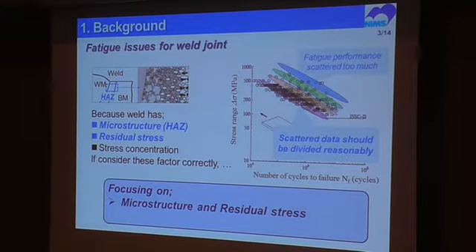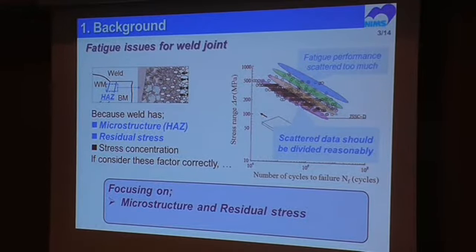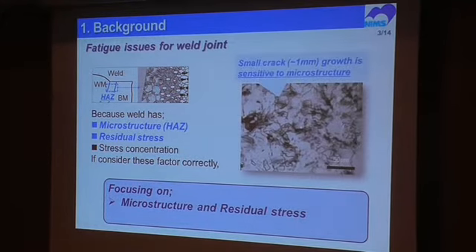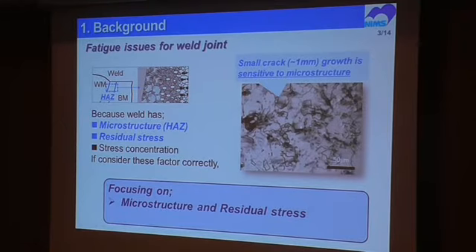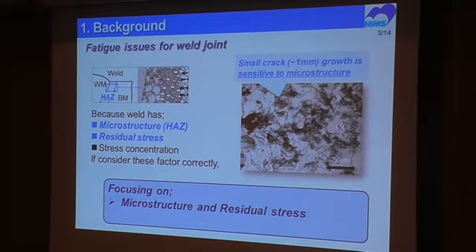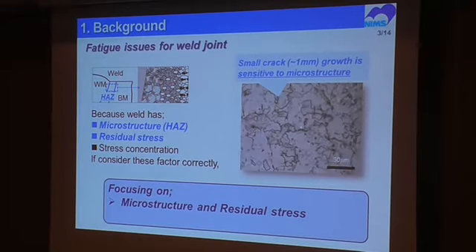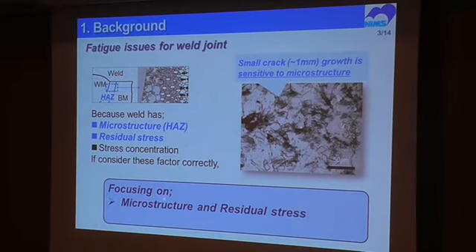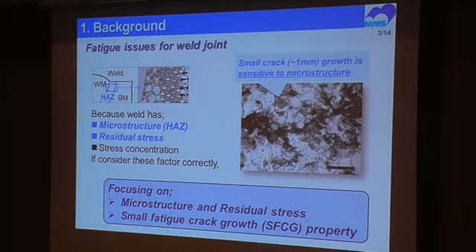So, to develop the evaluation method for these complex effective factors, this study is focusing on microstructure and residual stress as a first step. It is well known that small crack growth is sensitive to microstructure compared to long cracks. So, to clarify the microstructural effect, this study is also focusing on the small fatigue crack growth property of the material.